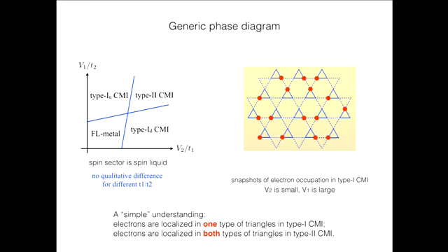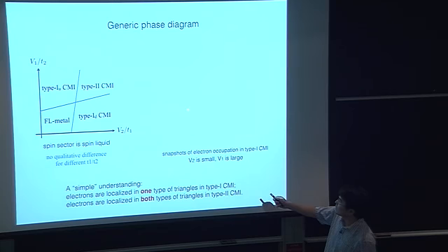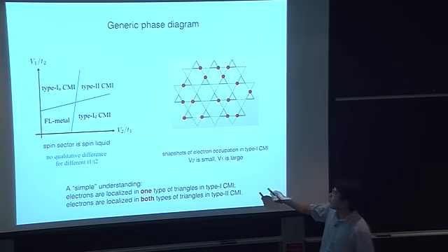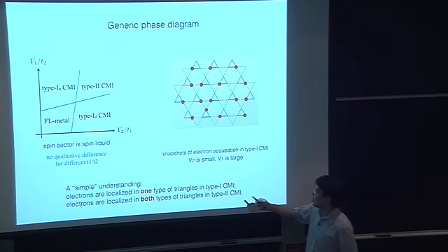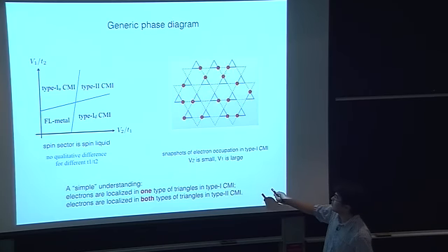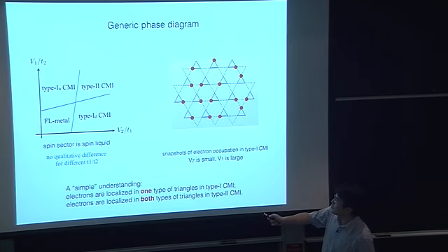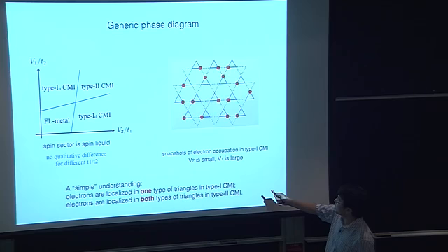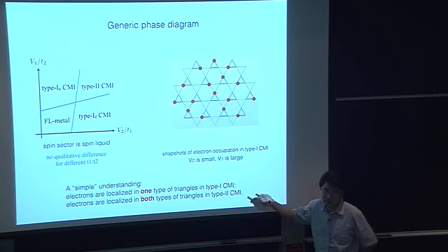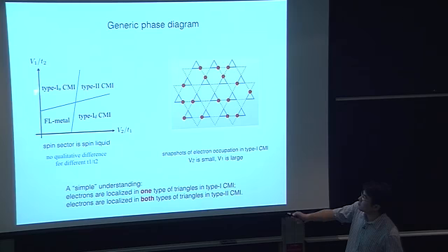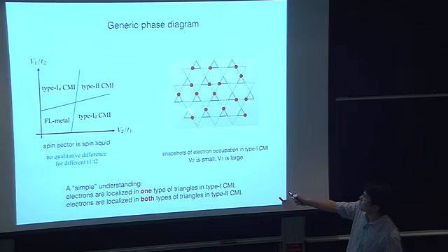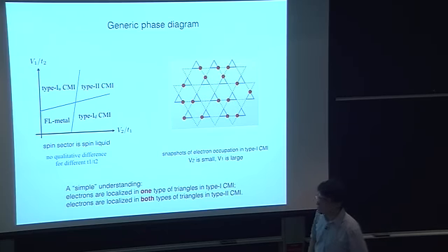the interaction on the up triangle is very strong, so it localizes the electron on the up triangle. The electron number on the up triangle is fixed to be 1. But the electron number on the down triangle is still fluctuating because V2 is small. It doesn't cost too much energy to place 2 electrons on the down triangle. In this regime, I call it a type 1 cluster Mott insulator, up. Electrons are localized on the up triangle, the electron number on the up triangle is fixed, so that's the insulating state.